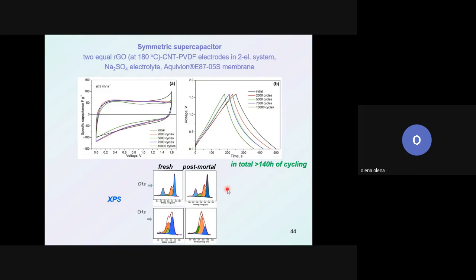And of course, our idea was to study XPS after. So this is for fresh electrodes, carbon and oxygen, and this is after cycling. So almost nothing happens in case of carbon, and I cannot say that something special happens with oxygen. So it's very chemically stable materials, and good electrochemical results can be obtained for that.